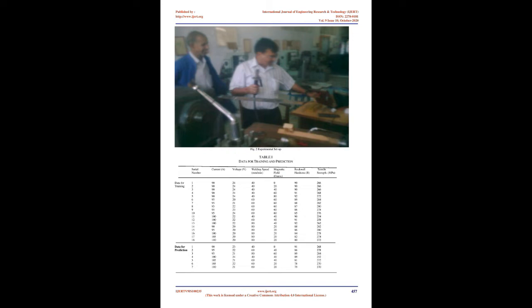The specimens for testing were sectioned to the required size from the joint comprising weld metal, heat-affected zone, and base metal regions and were polished using different grades of emery papers. Final polishing was done using the diamond compound, 1 µm particle size, in the disc polishing machine. The welded joints were sliced using power hacksaw and then machined to the required dimensions, 100 mm x 10 mm, for preparing tensile tests and 10 mm x 6 mm, for hardness test.